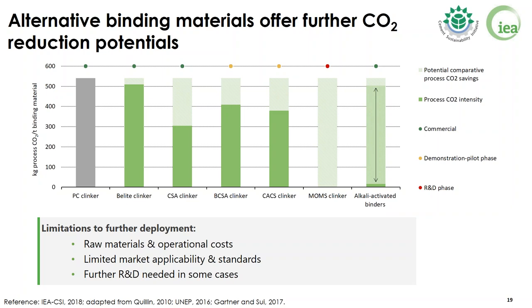Just to give you an example, this is a case of MOMS clinker. You can see from the graph, with this material, theoretically, we can displace 100% of CO2 emissions, but this material, that is a cement based on magnesium oxide derived from magnesium silicate, has some issues related to the high energy demand for transformation of the magnesium silicate to magnesium oxide. So it's not currently viable as a product. In this case, the almost full offsetting of CO2 emission is due to the fact that the material could absorb CO2 during the curing phase. But here we are still at an R&D stage.